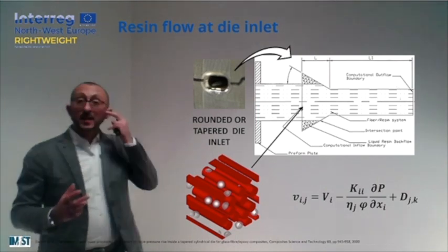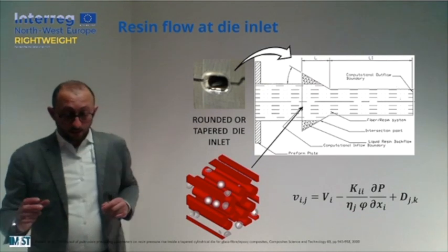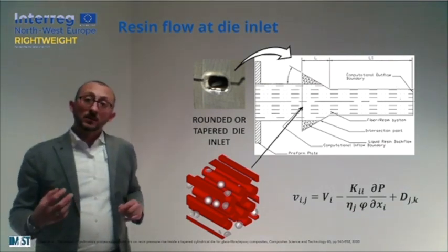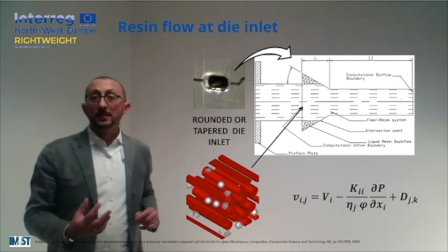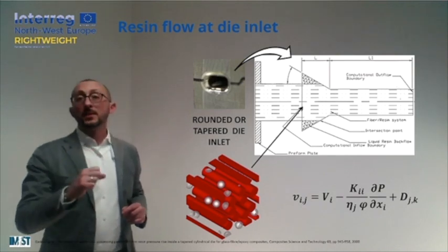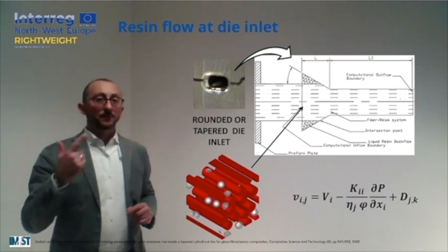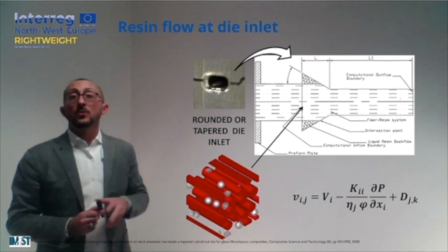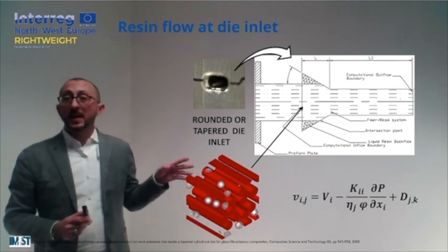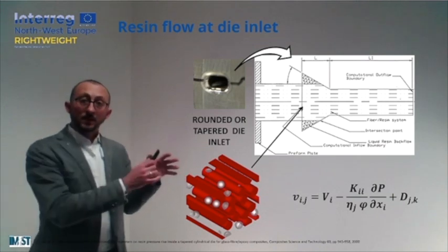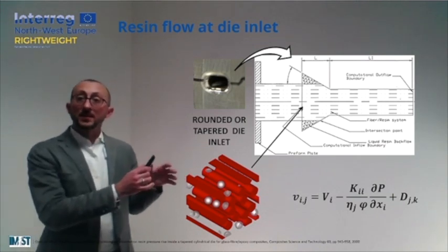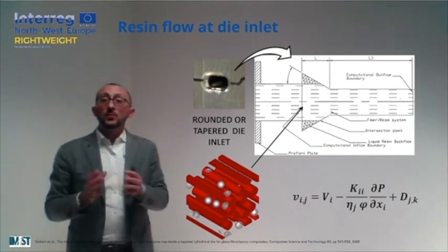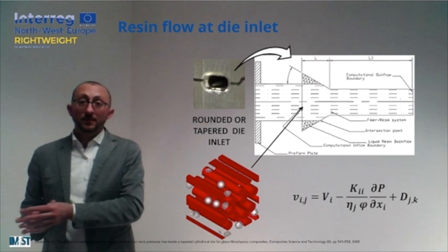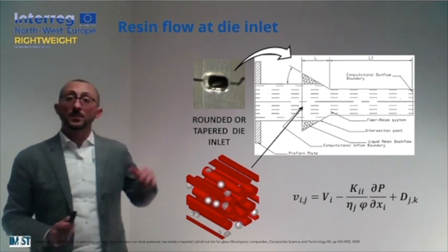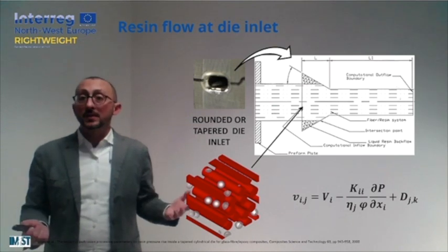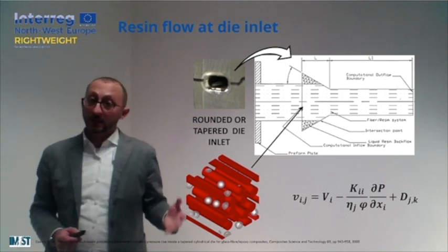Now, why this effect is quite interesting. If we go back to the impregnated tow at the exit of the open bath, in that moment we don't have just resin and fiber in our system. There are also some portion of air entrapped in this combination of resin and fibers. And we should be able to remove this amount of air from the material, otherwise at the end of the process we will find some voids in our pultruded composite material.